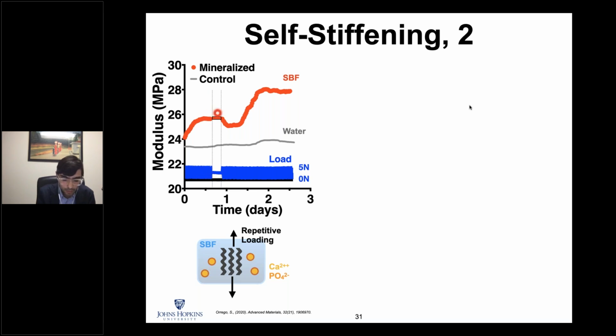We stop the load, then we have a slight reduction due to viscoelastic effects. As we begin to increase the load again, the stiffness of our material will increase, after reaching some plateau after 2 to 3 days, because there's no more mineral that can get deposited onto the surface—there's a saturation of materials.